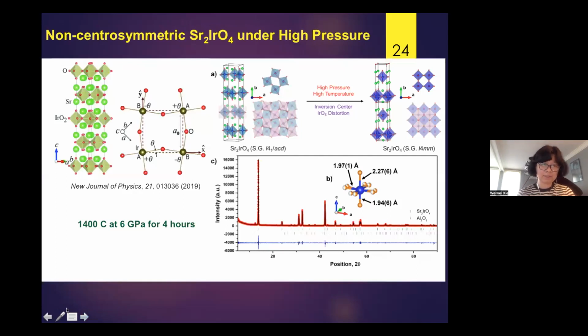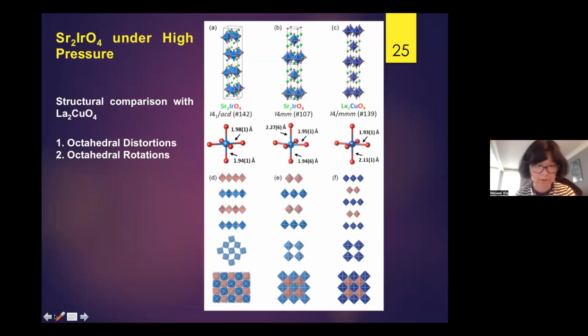At the same time, Maddie and I were interested in another system, strontium-2 iridium-O4, Sr2IrO4. People think this system is the closest to the cuprates, lanthanum-2 copper oxygen 4. However, if we compare the two structures, this is the ambient pressure phase, and this is for the cuprates. You see in strontium-2 iridium-O4 at ambient pressure, the iridium oxygen octahedra are rotated, and you can see that very clearly. However, for cuprates, it's regular, so there is no rotation.